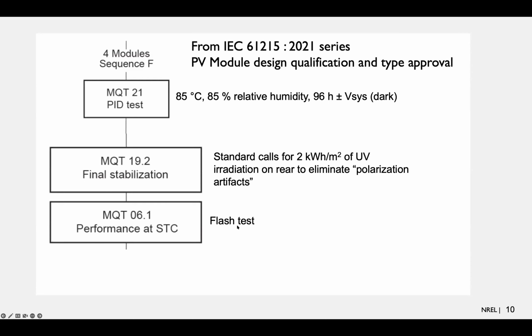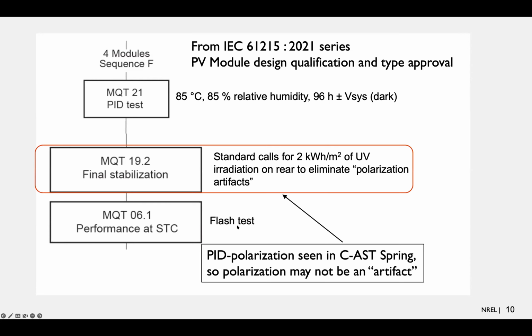And then there's a flash test. But the problem is when we do combined accelerated stress testing, we find PID polarization, and so this polarization may not be an artifact. It looks to me, based on the conditions we applied that are very realistic in the real world, that this PID polarization could happen on the rear of bifacial PERC modules in real life.